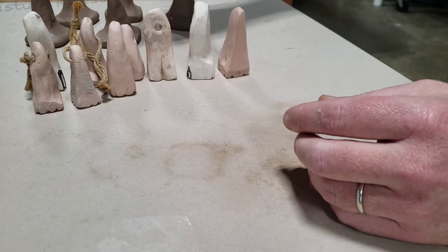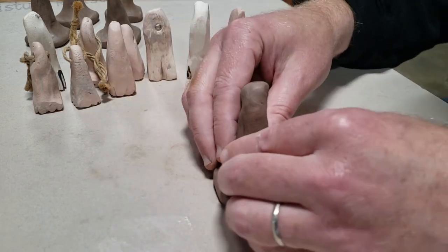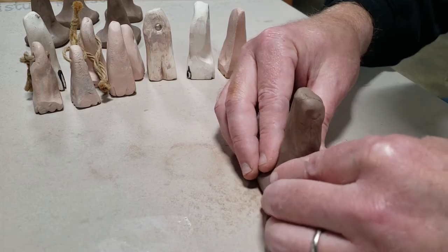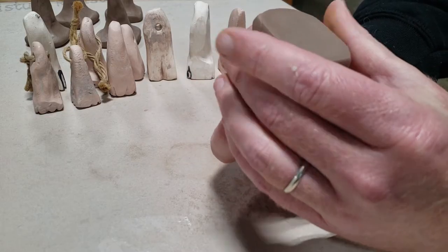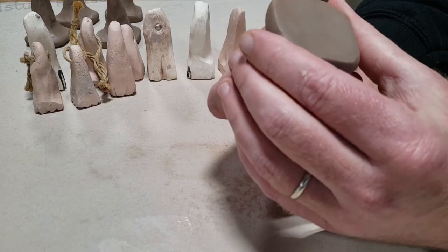After you make these initial shapes, just let these sit out. We want these to get a firm leather hard. When we start carving on these, you do not want any kind of sticky clay — it should just be dust coming off. So get some of those prepped, let them sit out for a while, and then we'll pick this up when these are nice and hard.